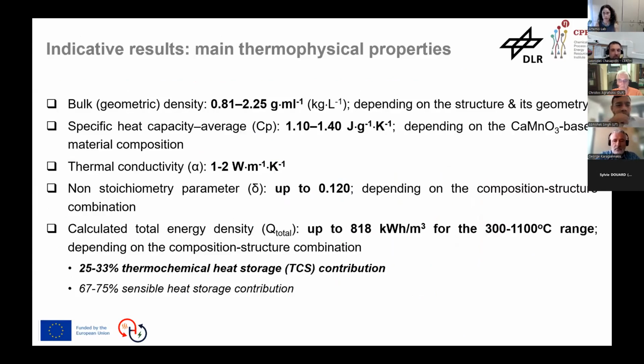The bulk density of the sample varies from 0.81 to 2.25 kilograms per liter, depending on the structure and geometry. Specific heat capacity ranges from 1.1 to 1.4 joule per gram Kelvin, and the thermal conductivity between 1 to 2 watts per meter Kelvin. The non-stoichiometric parameter delta reaches up to 0.12, depending on material composition.